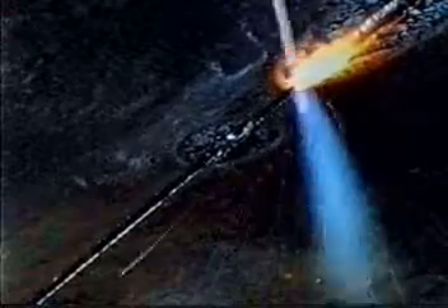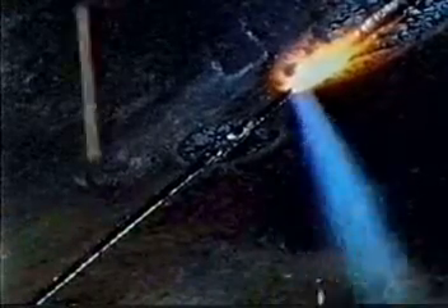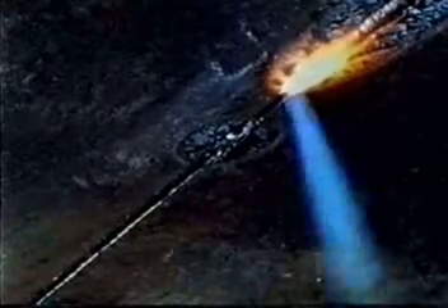In all rightward welding, it's essential to keep the weld pool as short as possible. Fusion and penetration are completely controlled. There's no difficulty in seeing all the weld area as it's not obscured by rod or flame. The slight increase in the gap, known as the onion, means fully melted root edges and sound penetration. From underneath, the control and consistency of full penetration are self-evident.